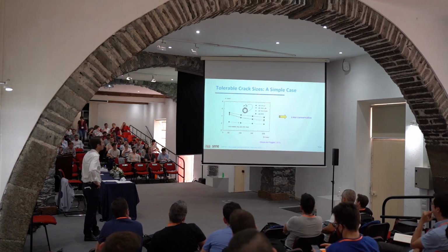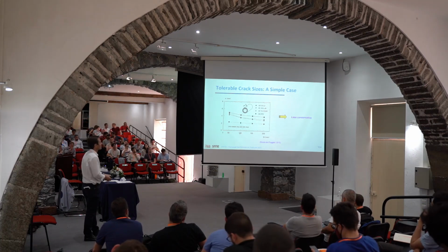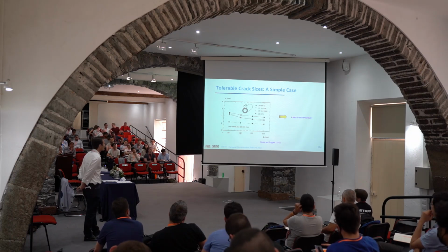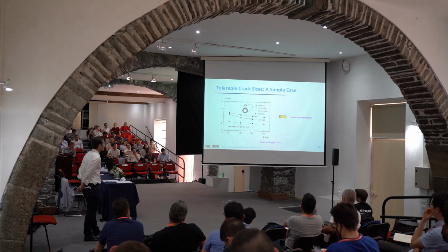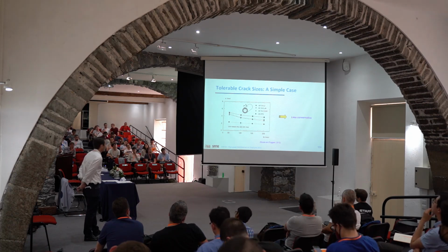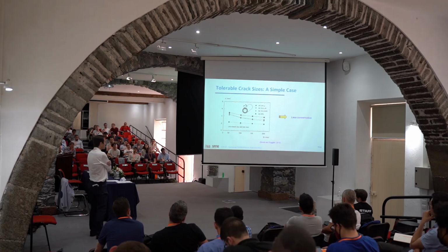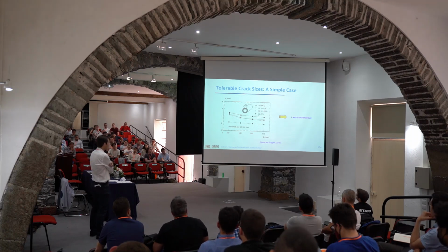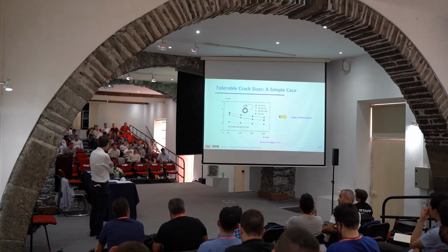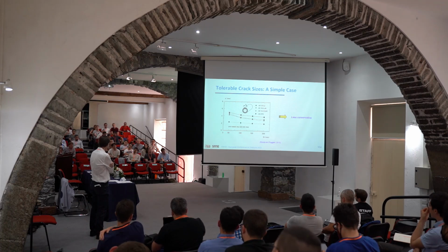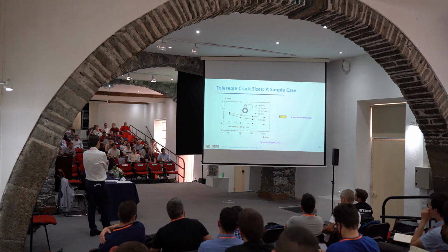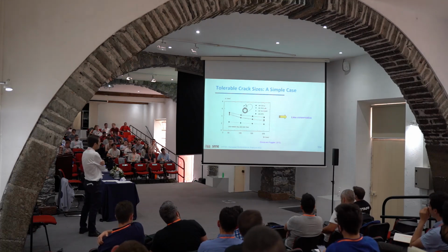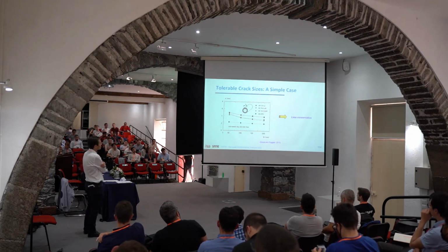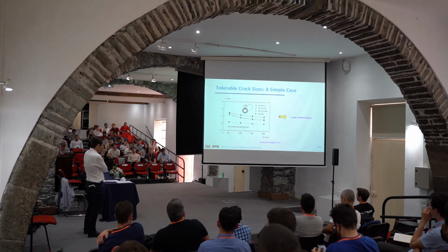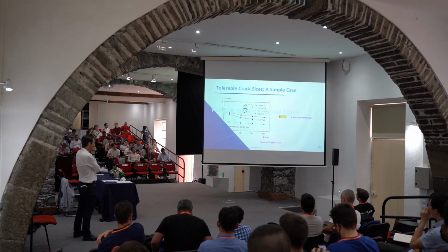Here is API 579, for example, for a crack size with 100 millimeter length. The maximum tolerable depth would be 2.2 millimeter. If you use the advanced procedure, taking into account detailed finite element analysis, equivalent stress-strain relationship, etc., you'd get more than double the tolerable crack size. So you see a very huge saving in your installation process because your tolerable crack size is much more refined.